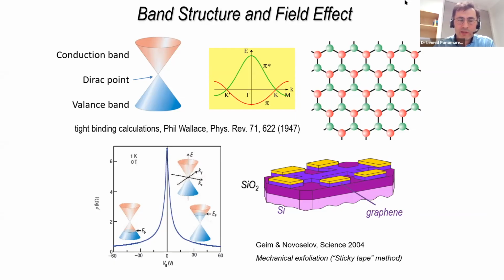They will be covered, of course, immediately in a nanolayer of water and everything that is flying in the air, which will dope graphene. So if we measure the resistance of graphene over time, the resistance will change, but only due to doping, which we can remove, for example, by slightly warming it up or putting it in a vacuum. If we, for example, encapsulate graphene in boron nitride on both sides, then it will just stay in the same form essentially forever.